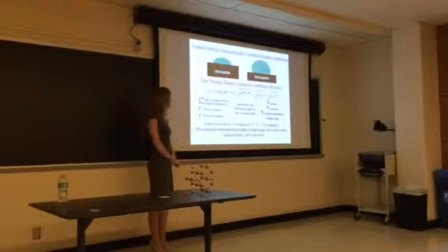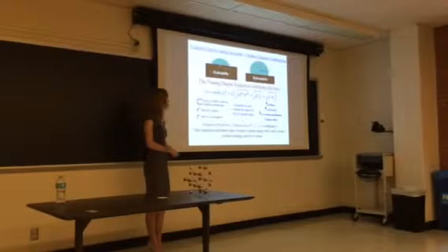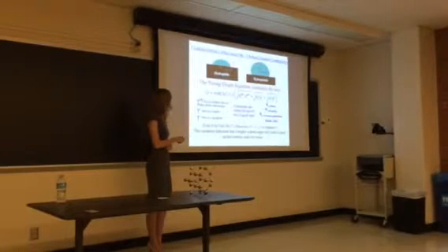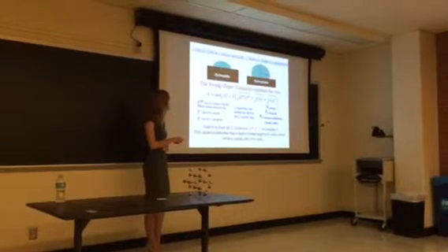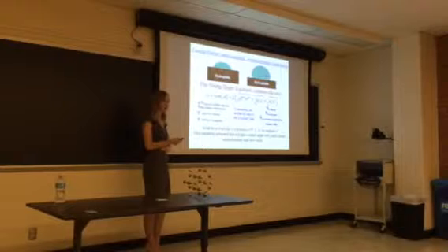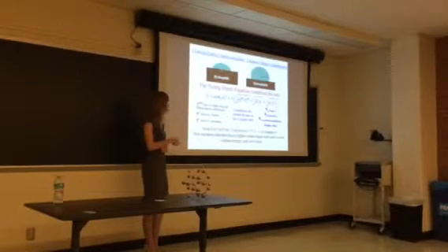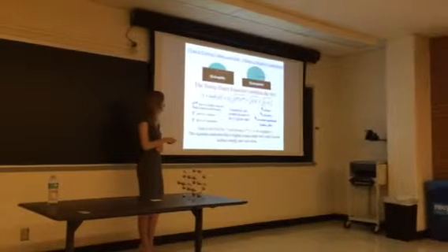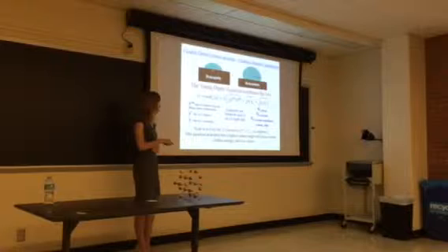So we use the Young-Dupré equation, which combines both the Young equation and the Van Oss theory. And so here we have a very simple relationship that includes our electron donors, acceptors, and Lifshitz-van der Waals contribution, as well as our contact angle here. So what we do is we measure the contact angles created by our three liquids on our silicon surface, and then we have an equation for each, and using a system of equations, we solve for our three unknowns in order to compute gamma T.